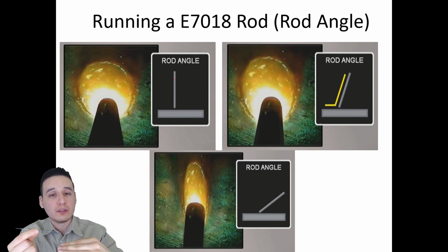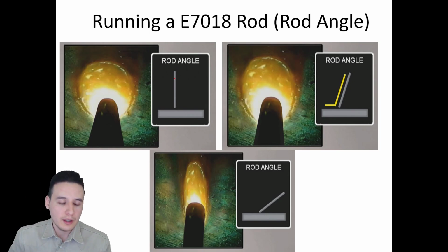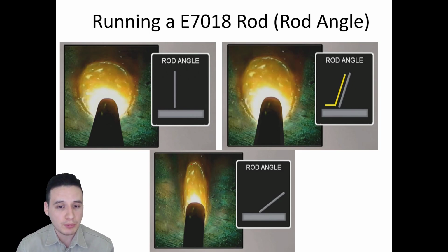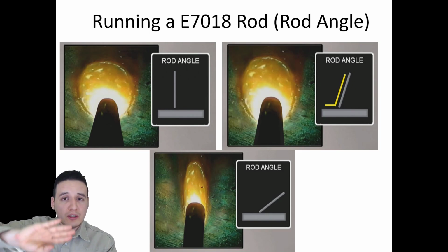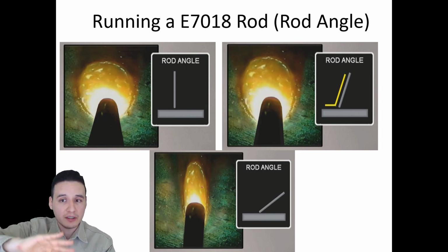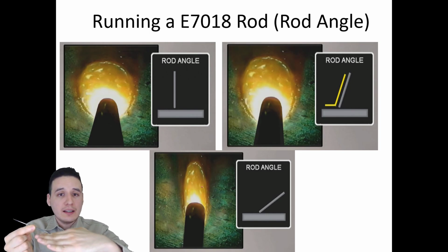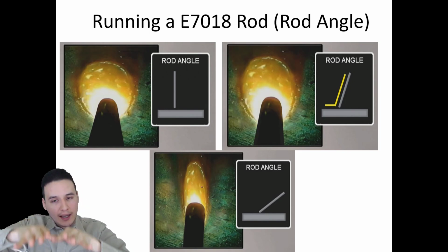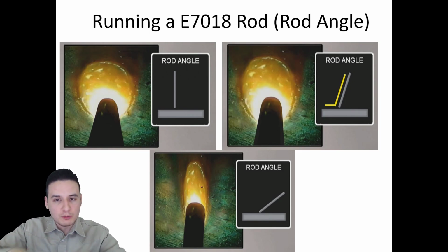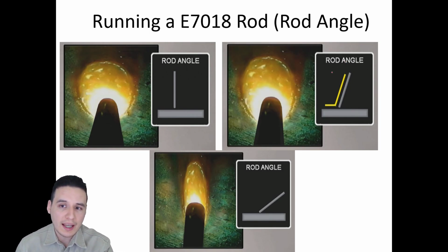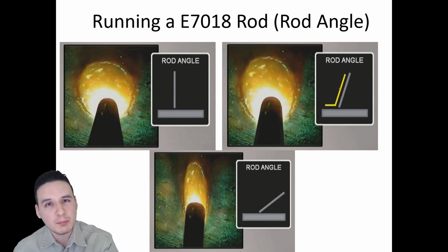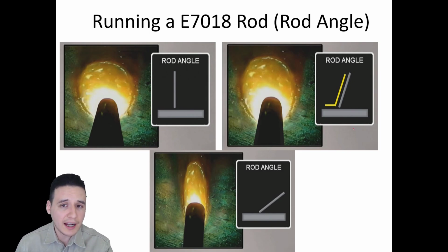However, you can't have too drastic an angle like this, because if you do, this will happen. Just like in this illustration, see how that puddle tends to get really elongated? And if you have an elongated puddle like this, your bead will crown up quite a bit down the center. The more you angle your rod this way, the flatter and more even your bead is going to be. So that's why we want a drag angle somewhere in between, not completely straight, but not way too much. About 10 to 15 degrees is the ideal.